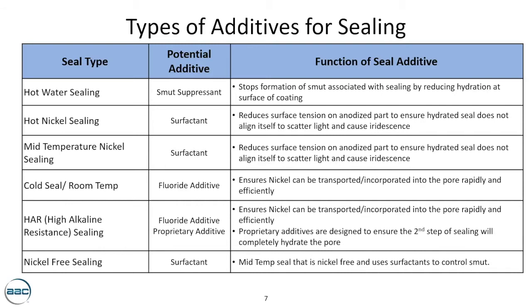What can be a challenge with the cold seal as a counter, though, is if an aluminum part is dropped into that bath, or there's something that consumes the fluoride, you will have to ensure you measure that to make sure it's in line. But as a rule, managing the fluoride is much easier than dealing with the surfactants associated with mid-temp and hot nickel.